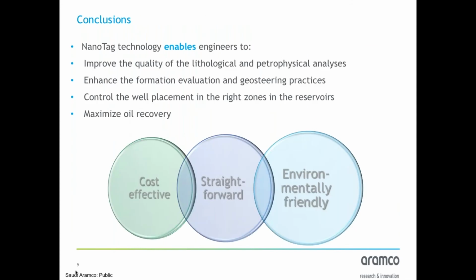To sum up, a barcodable polymeric nanoparticle design as tags for drill cuttings was synthesized and tested in the lab. A drilling field test confirmed the compatibility of the nanotags to determine the exact depth of origin of the drill cuttings in real time. And the impact of this is that the nanotags approach has potential to be a game changer in the oil industry, allowing accurate and precise cutting depth determination for real-time characterization from the cuttings.